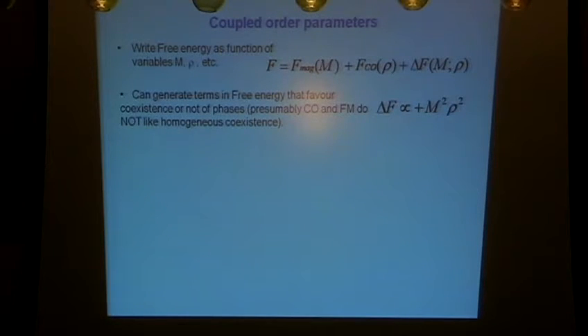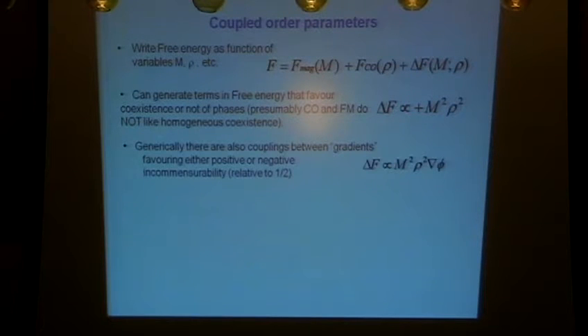So the natural thing, of course, is to have a free energy cost which doesn't like the two order parameters to coexist. So that's very natural. That has a positive term, that's a penalty, and so that will generally keep them apart. And if you just have this term in the Ginzburg-Landau free energy, you will get a first order transition between one phase and the other. If you ask what the next order term is, however, the next order term is a term which couples gradients. And the leading term which couples gradients is in fact linear in gradient and quadratic in both order parameters.